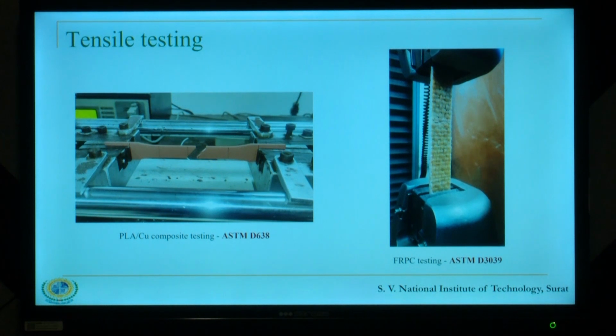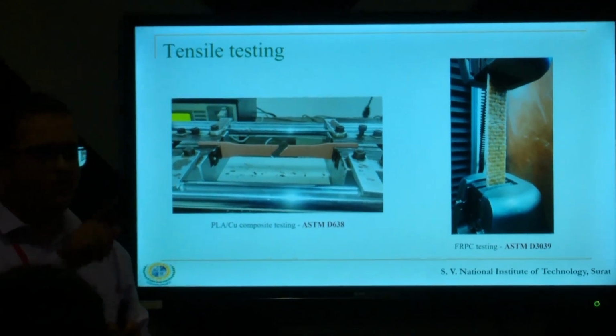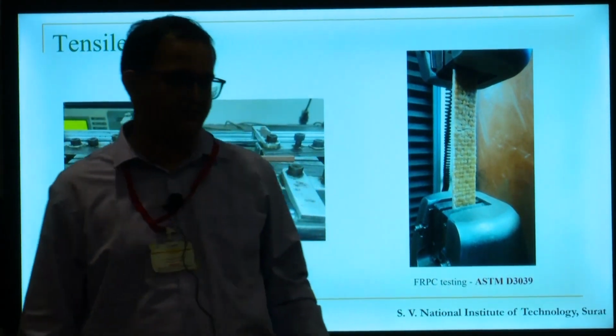So, I think this is the copper infill PLA copper, okay, and this one is the natural fiber, I suppose, jute and flax. See, the thing is, the dimensions, you get a certain range into it. When we are going for the cutting, if you are going with a certain size of the fabric and you are cutting it into the minimum size, then you get only 2 strands of it. You may cut it this way, so you will get only this much portion. That will not help us get the desired result, because it is going to fail immediately, it is going to get delaminated very soon. So extreme dimensions you can go for.